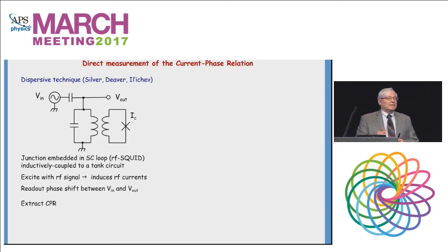There are high-frequency techniques, and I'm going to get to the point that I think she was heading toward, which is that frequency really matters in measuring these current phase relations in some cases. So this is a dispersive technique developed by Arnold Silver, Bascom Deaver, and recently exploited by Il'ichev. In this case, you drive an RF current, look at the screening currents, very much like in the screening experiments, but you do that at higher frequencies.